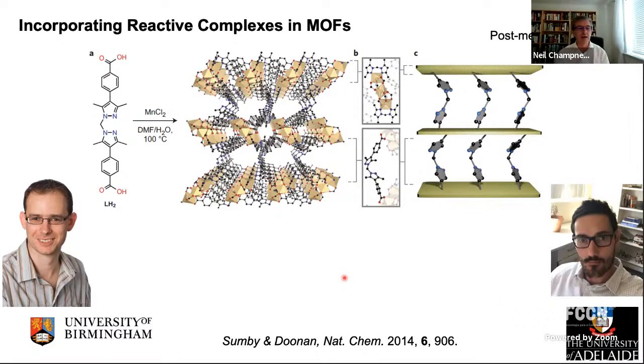And right at that time, they just were in the process of publishing this paper. And this paper's a really fascinating piece of work. And as you will see, we've gone on to develop some of the chemistry first described in this paper. And what they did was they took this ligand here, which you can see is a dicarboxylate that has this vacant bis-pyrazole site in the middle. And you can react this with manganese(II), just as we've done. And it makes a MOF structure.